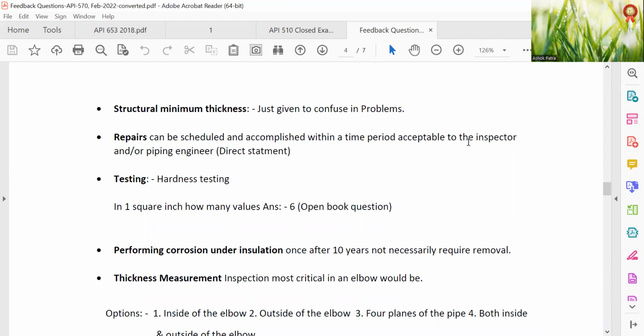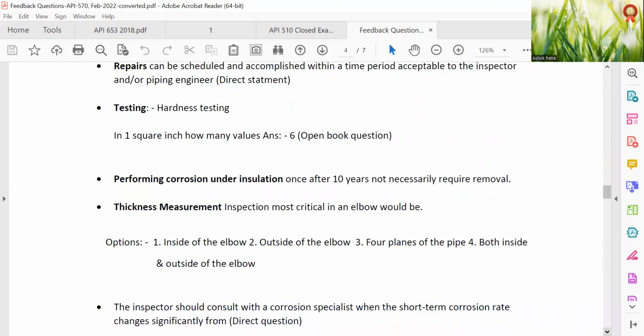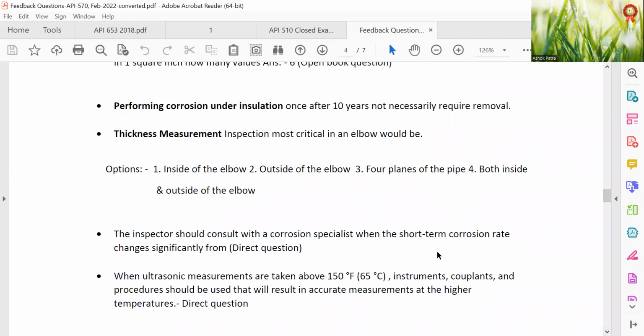Thickness measurement inspection must be most critical, and an elbow would be inside of the elbow, outside. 4 planes of the pipe, both inside and outside of the elbow. The inspector should consult with a corrosion specialist when the short-term corrosion rate changes significantly. Direct question. For an ultrasonic measurement taken above 150 degrees Fahrenheit, 65 degrees centigrade, an instrument and couplant procedure should be used that will result in accurate measurements at the higher temperature. Direct question.